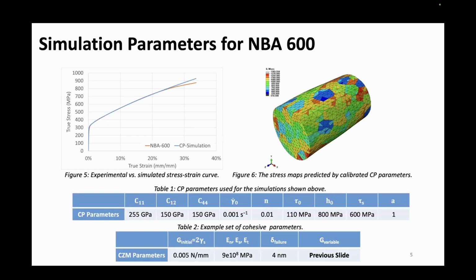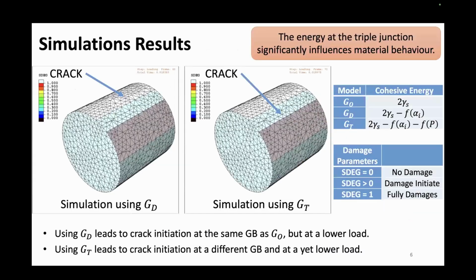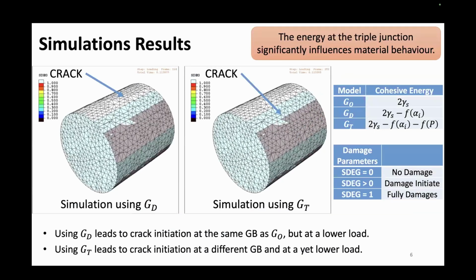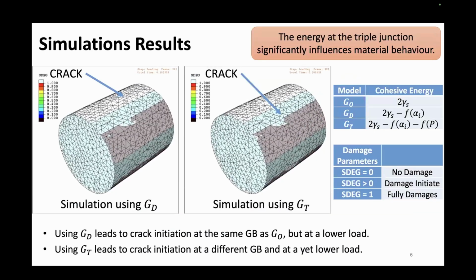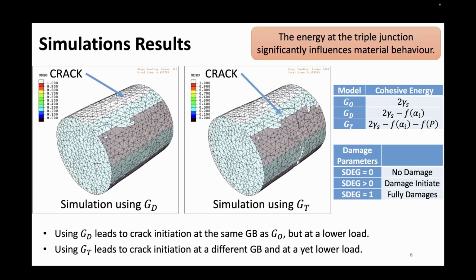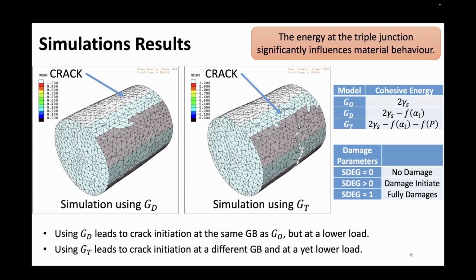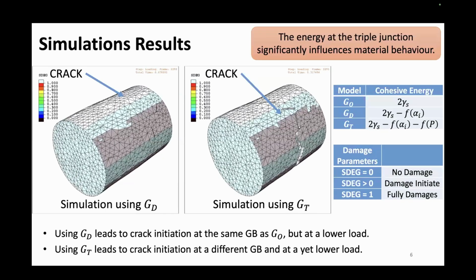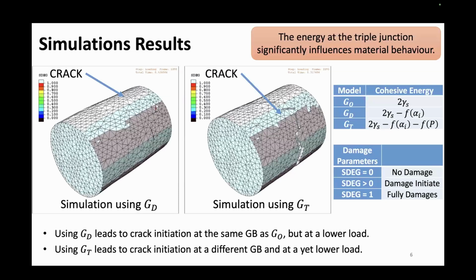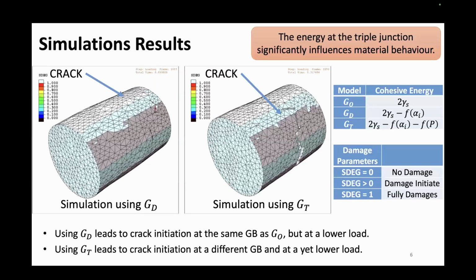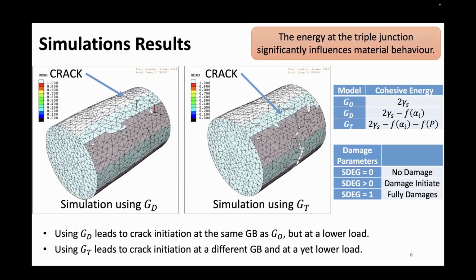And then we move from the crystal plasticity model to crystal plasticity and cohesive zone modeling. One set of the cohesive parameters we use is listed in table 2. Note that the G is variable, which depends on the three methods we just discussed in the previous slide. So here is our simulation result. On the left-hand side is a simulation based on the disorientation angle, and on the right-hand side is a simulation based on the triple junction disclination power.